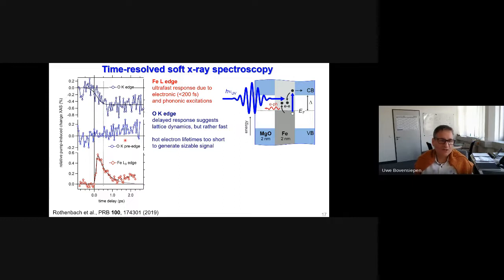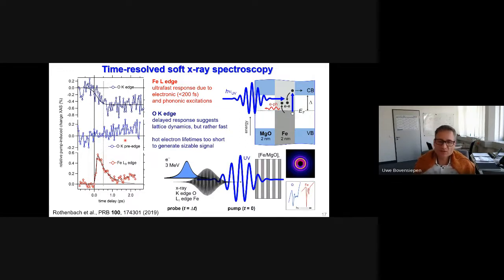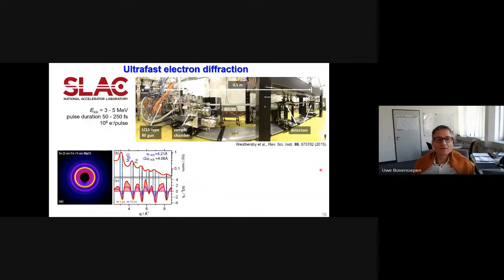So if this is indeed a response of the lattice, it would be interesting to look at the lattice directly. And this we can do by an experiment where we transmit short electron pulses through this heterostructure. So I will show you data with electron diffraction. Remember, Klaus Sokolowski-Tinten is an expert on this, and he uses these mega electron volt kinetic energy electrons as short pulses and transmits them through this heterostructure. And this is a diffraction image that he can then record. This is something we do in Northern California at the Stanford Linear Accelerator Lab, where there is this still more or less unique user facility. There is this RF gun, which emits short pulses of electrons here into the sample chamber, and there are two detectors here. So if you're interested, you can look into this reference.